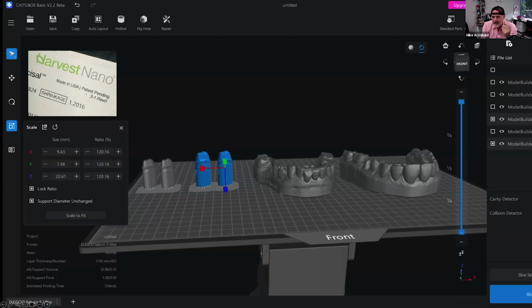Now that's cool, because then we can go in and we can pencil line our margin on our enlarged die. We can seat the green state to it. Now we have some stability to it. We can carefully go in, and just with polishing instruments, we can polish and finish that cervical half contour to a perfect emergence, an ideal emergence. So we have an actual flawless margin that comes out of the sintering furnace. And we were very excited to see if that materialized and it fit perfectly, and it did.